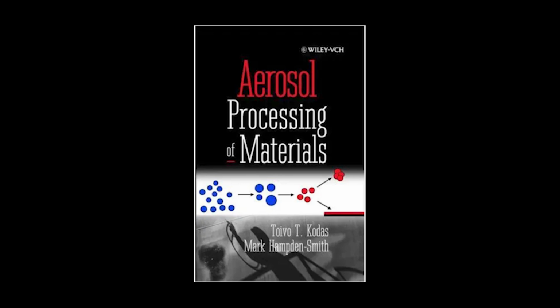Just to maintain their current size, let alone grow. If the supersaturation is only moderate, the smallest particles will immediately start to evaporate or sublime, giving their mass back to the gas phase. It's like the constant threat of extinction for the smallest building blocks. It is. The Kelvin effect establishes a critical particle size. Below that size, which might be around 1 nanometer for something like TiO2, the particle simply isn't stable and can't survive. It's forced to evaporate.